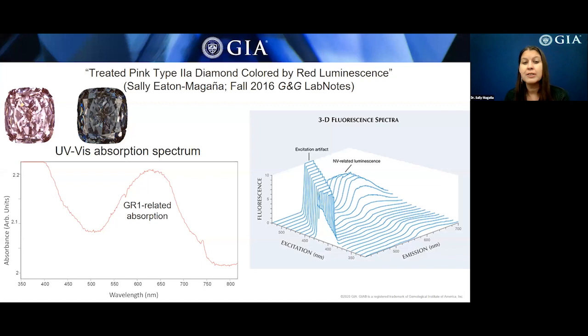On the right, we show a 3D plot that shows nitrogen vacancy luminescence that is created by excitation at many different wavelengths. This is meant to illustrate that the nitrogen vacancy luminescence is actually stronger when excitation is from blue light, say 450 to 500 nanometers, than from the ultraviolet wavelengths. And this strong emission stimulated by daylight indicates that the diamond is colored by that red fluorescence or luminescence in response to blue light, and to a lesser extent by the fluorescence due to the UV component in daylight. And so this was definitely an interesting surprise when it came into our lab. And to my knowledge, it's still the only treated diamond that I'm aware of that has shown this behavior and such an alexandrite effect.